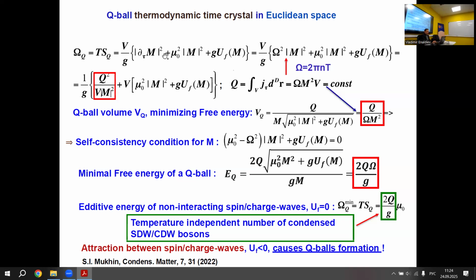So now let us minimize, let us do the following. You see this is the first derivative over Matsubara time modulus squared. So it gives you omega squared m squared. And now if you use this relation, the Q charge conservation, this Noether charge conservation, you can substitute this omega squared with this expression, and you see volume appears in the denominator. Here, volume is in the numerator. And if this expression is positive, you have really a minimum at finite V. And this is the Q-ball creation event. So you can find the volume V, which is finite, that minimizes this effective Euclidean action of the M field.